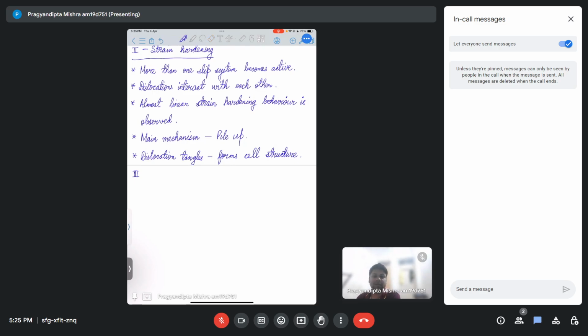So what happens in dynamic recovery then? It is characterized by a decreasing rate of strain hardening. Okay. So now the strain hardening rate will start decreasing, and cross slip will take over. Over pile up, now cross slip will take over, and that will release all the stresses that were accumulated due to pile up. Okay. So essentially, this stage is known as dynamic recovery.